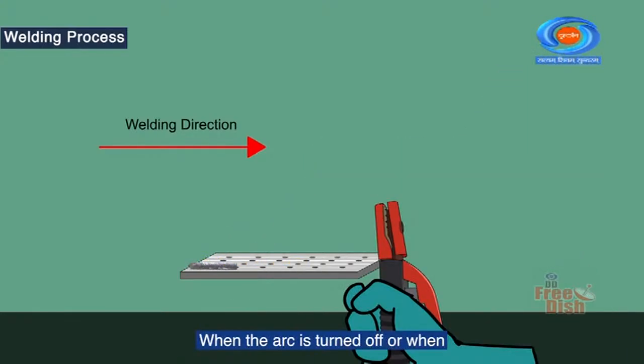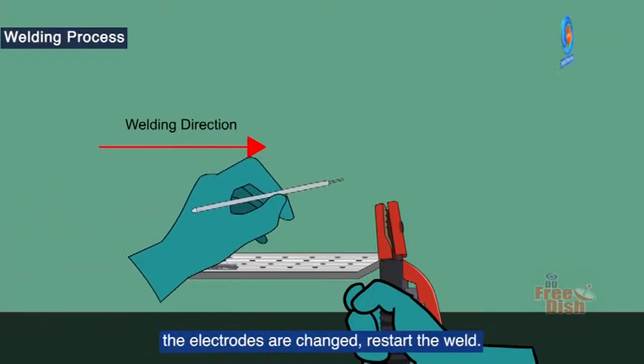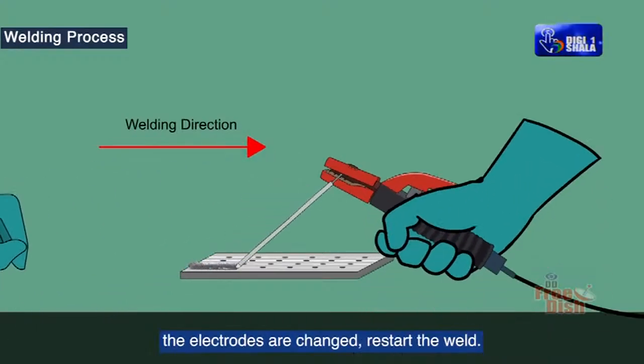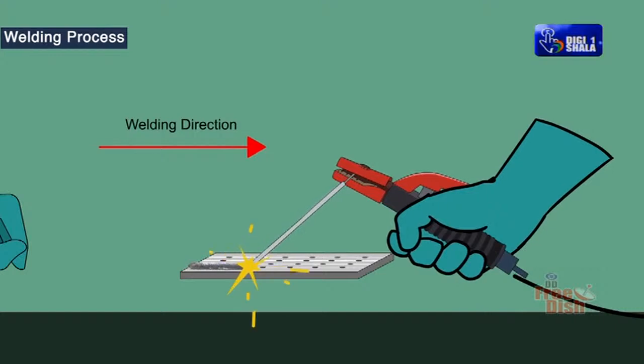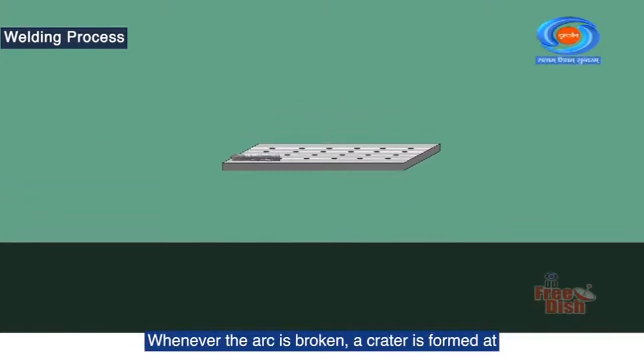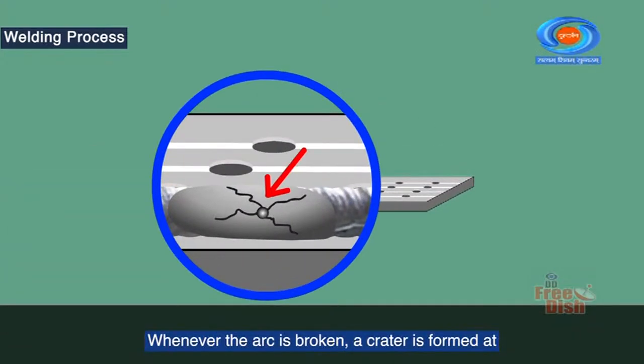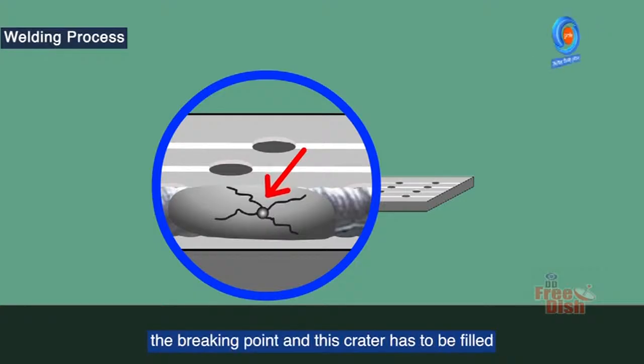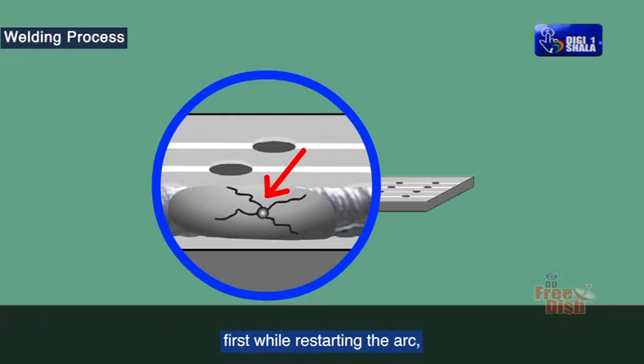When the arc is turned off or when the electrodes are changed, restart the weld. Whenever the arc is broken, a crater is formed at the breaking point, and this crater has to be filled first while restarting the arc.